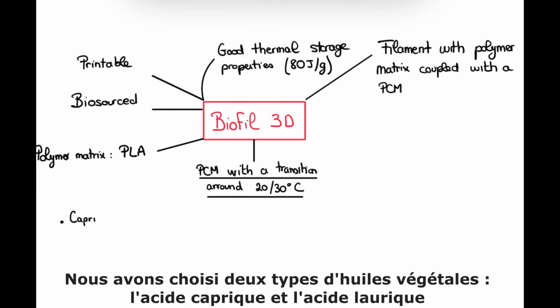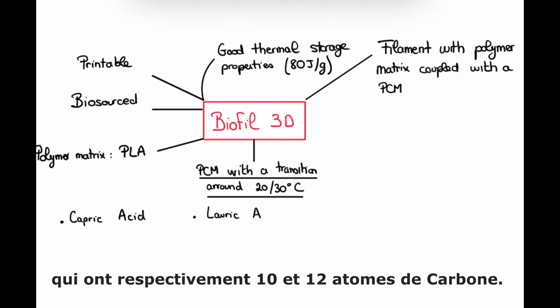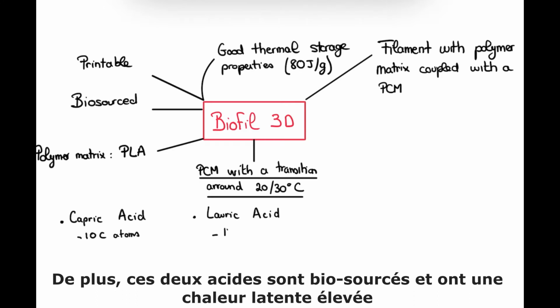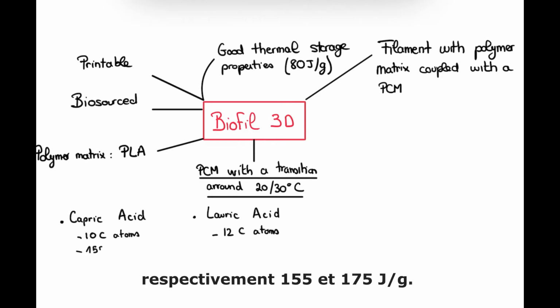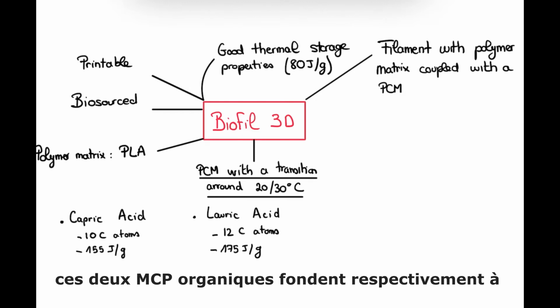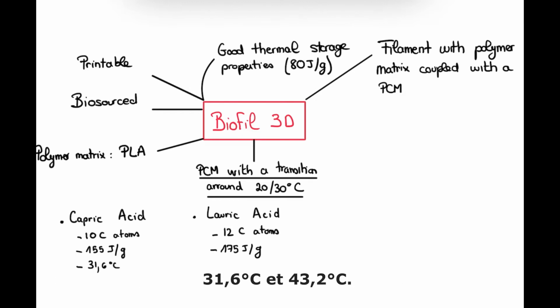Therefore, we choose two types of plant-based oils, capric acid and lauric acid, respectively with 10 and 12 carbon atoms. Both of these acids are biosourced and have a high latent heat, respectively 155 and 175 joules per gram. Note also that these two organic PCMs melt respectively at 31.6 degrees Celsius and 43.2 degrees Celsius.